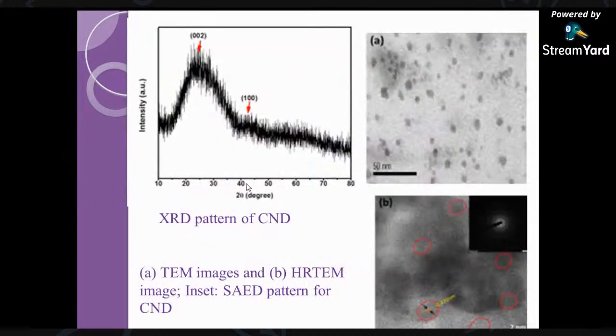Okay. So this is the XRD pattern that you can see for carbon nanodots. You have an amorphous structure for carbon nanodots. This indicates, in the TEM images you can see, that the carbon nanodots are uniformly dispersed, with a size of 1 to 4 nanometers on average. Here you can see the graphitic layer of carbon, indicating the interplanar structure.